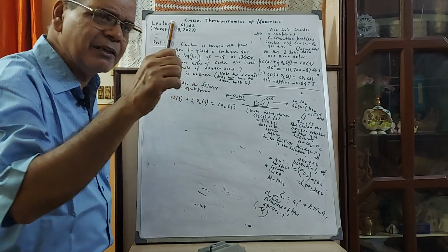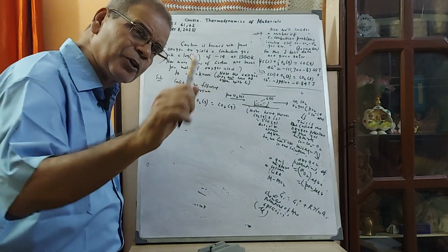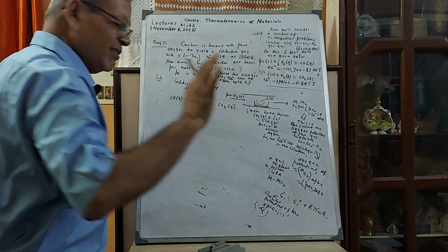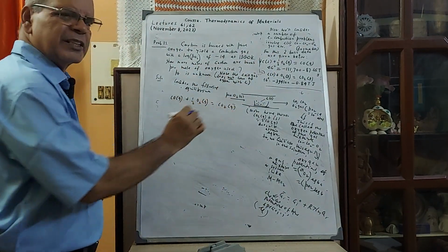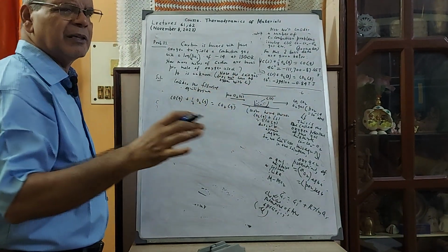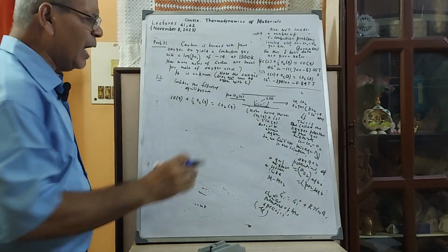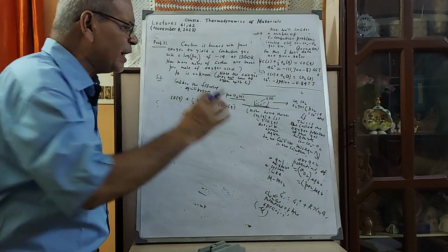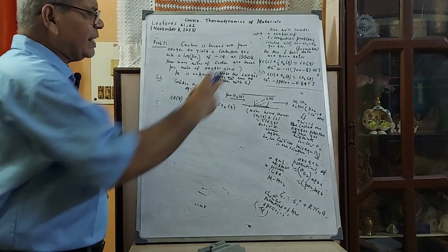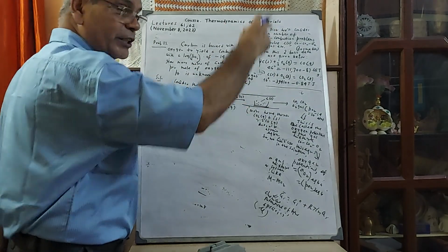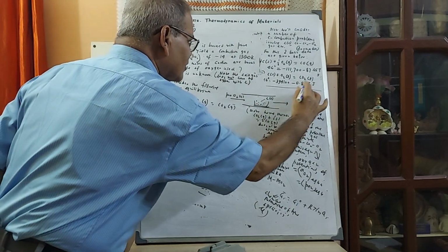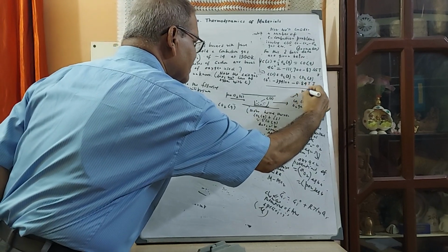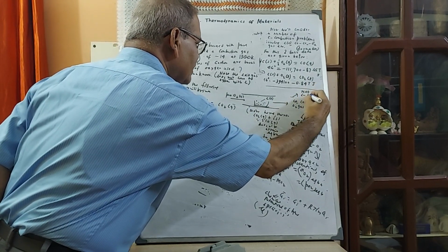So I am not saying chemical potential; it is oxygen potential. Similarly, carbon potential is there. When we speak of oxygen potential, oxygen must be present in the system. Enough, so consider this equilibrium. I'm giving you that there is this gas mixture. I'm not hiding or tricking you. It is not in equilibrium with carbon, which means it is not a carbon saturated gas. Equilibrium with carbon means carbon saturated; this is not a carbon saturated gas. This is an example of why it is not saturated.